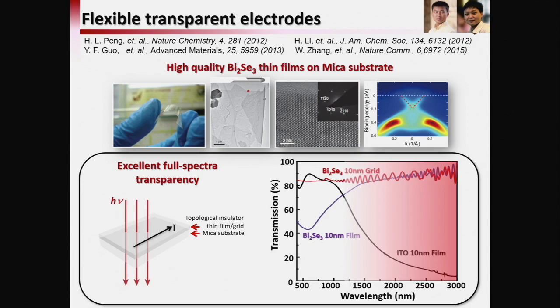Okay, great. So you can see that the transparency in the IR region is much better than the thing we use now, indium tin oxide, right? ITO. Now, each of us has a cell phone, and this is the transparent electrode on the top. However, in the visible range, the transmission is low because this bismuth selenide is a small band gap semiconductor. This is beyond its bulk band gap. This is understandable, and we can improve that by making the bismuth selenide thin film into a grid. And then in the whole spectrum range, it achieves very high transparency.